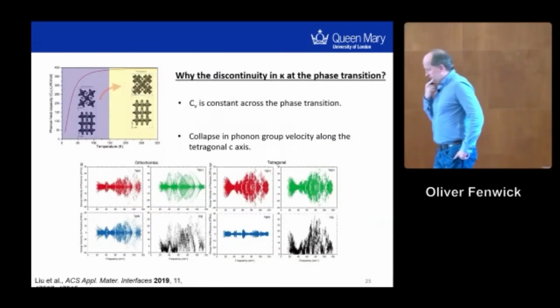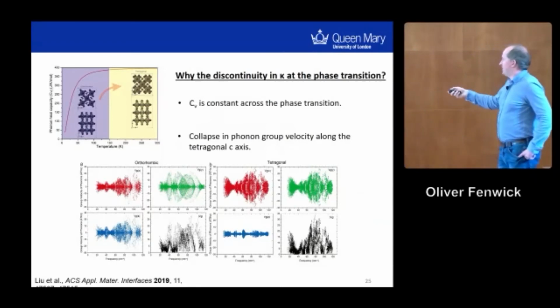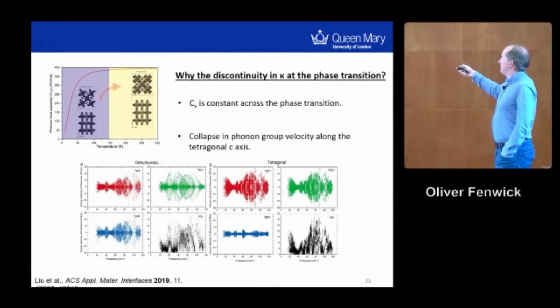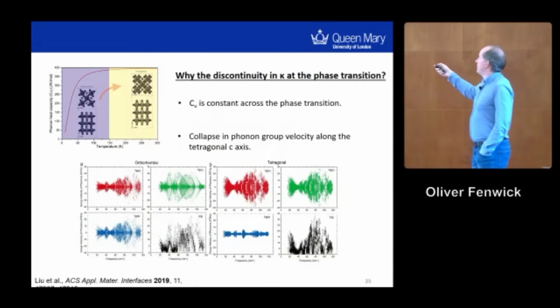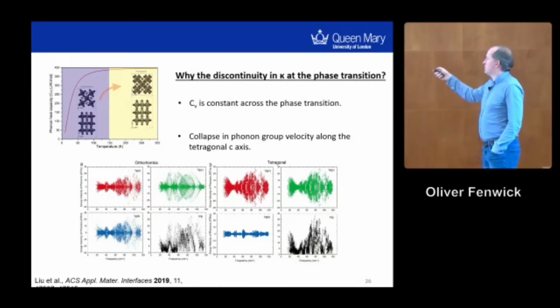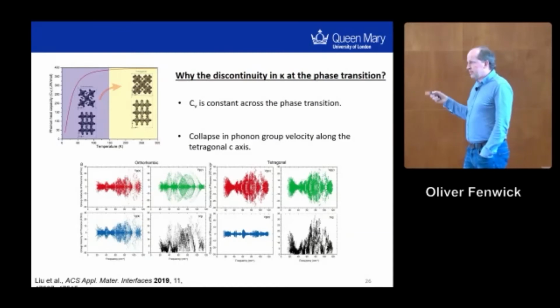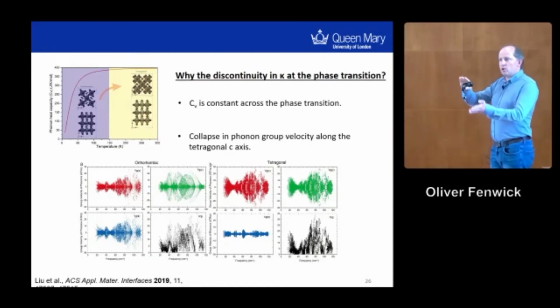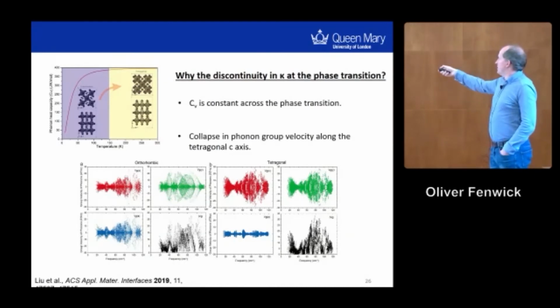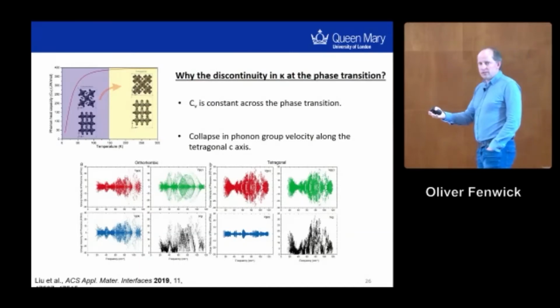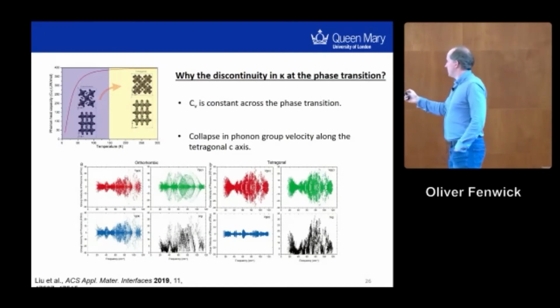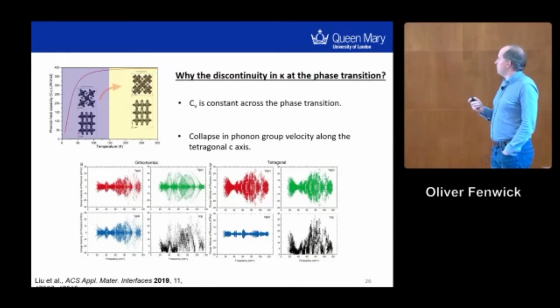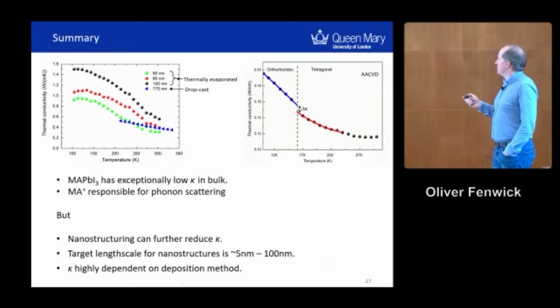The other one was what happens at the phase transition. Well, for this, we went back to the density functional first principles calculations. They told us there's not a change in heat capacity across the phase transition. On the other hand, there is a collapse in the phonon group velocity along one axis of the crystal, along the C-axis. And that seems to be driving it. We don't see it in the evaporated thin films because the orientation of the crystallites is such that the C-axis is pointing out of plane, so we don't measure the thermal transport along that direction. But in the mixed orientation film from the AACVD, we do see the effect of this collapse in phonon group velocity. So good, our data wasn't so crazy, we can explain it.